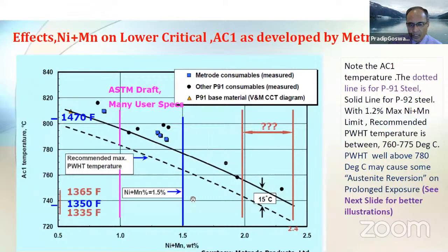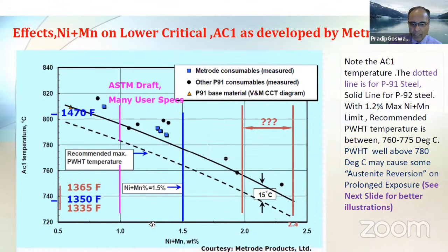Later, after looking at all the pros and cons, after looking at the difficulties, they decided to restrict this nickel plus manganese to 1.2% maximum, and typically 1%. So when it is between 1.0 and 1.2%, one gets an AC1 temperature close to 780 or more, above 780. We'll see the next slide.